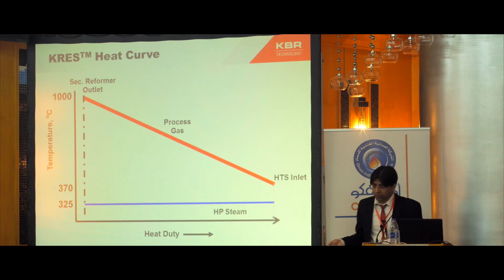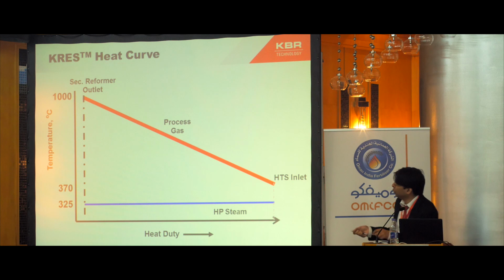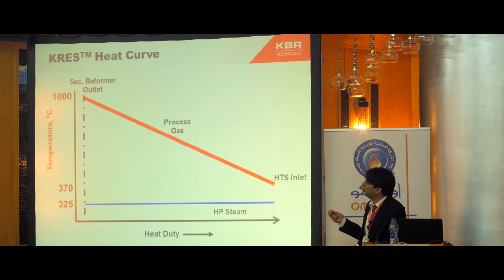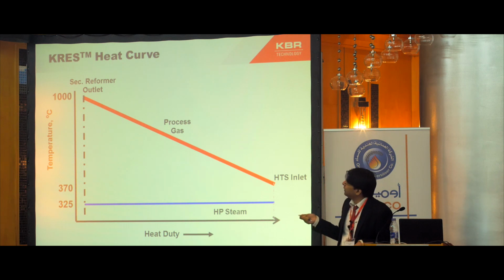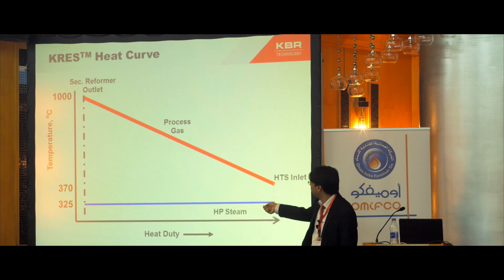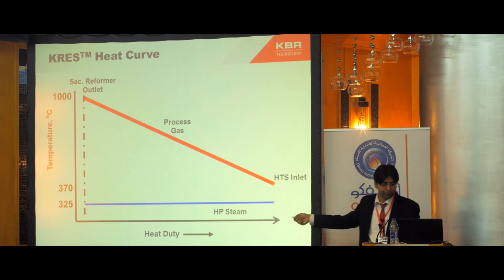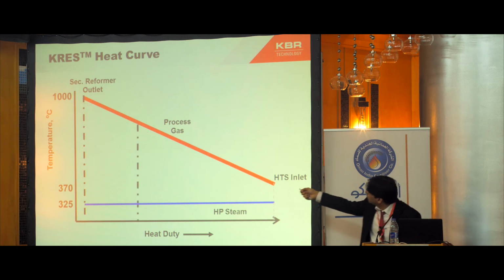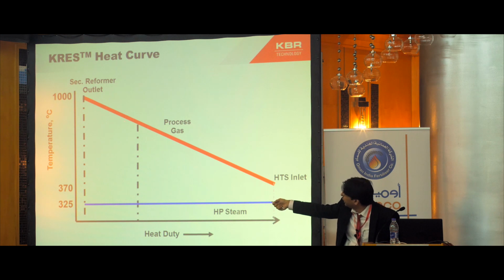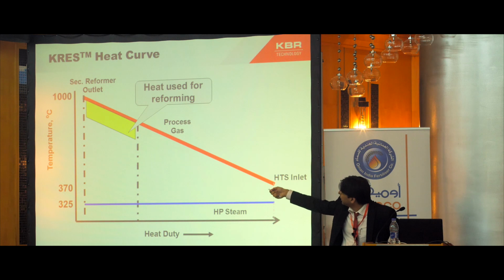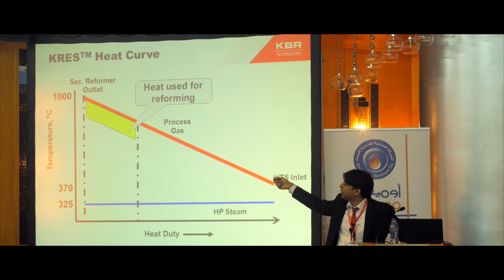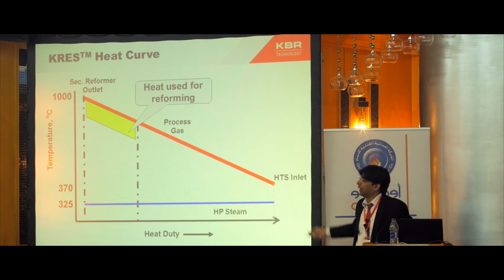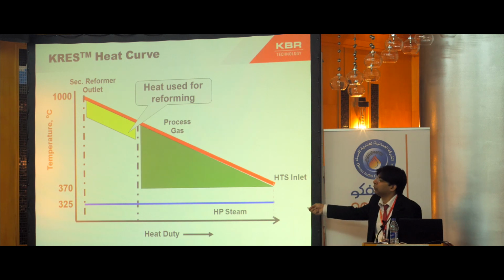The fundamental behind using this KRES technology is using the high grade heat from the secondary reformer effluent for reforming. Conventionally, the secondary reformer outlet at 1000 degrees C was used for generation of high pressure steam. So earlier, all this heat available was used to generate high pressure steam. But this is extremely high grade heat, which can be used for reforming. This is what the concept of KRES lies in. Use the secondary reformer outlet gas, which is at 1000 degrees C, for the reforming reactions. KRES essentially does that. The rest of the heat is still used for the high pressure steam generation.